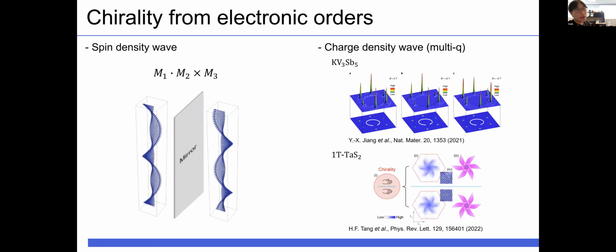There are two examples of how chiral symmetry can be broken in a crystal. The first one is spin density wave. A spin density wave system is chiral when the spin density wave can be expressed by a product of three non-coplanar vectors. The other example is charge density wave. It is known that in the kagome material potassium vanadium antimonide, KV3Sb5, and the transition metal dichalcogenide 1T tantalum disulfide, there is a chiral charge density wave. But it's a little tricky to think of chirality in charge density wave because charge density wave is a scalar quantity. So similar to the spin density wave case, we should consider three non-coplanar vectors. Chirality in multi-Q charge density wave materials can be realized by three propagation vectors.